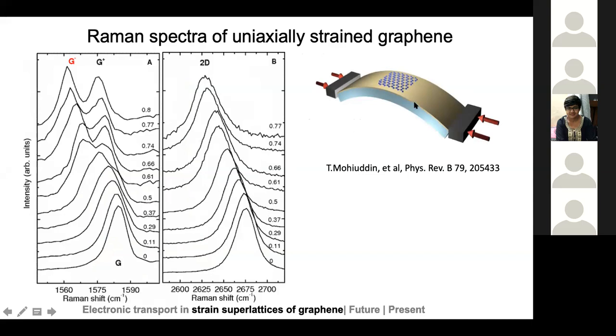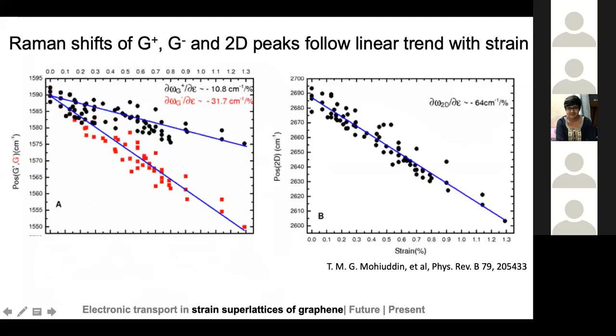In these experiments, different flexible substrates were used for bending graphene. And what was found was, in this graph, again, you have the intensity on the y-axis, the Raman shift on the x-axis. And what you'll find is as you increase the strain in the system, which corresponds to these different curves in the upward direction, the G peak slowly splits into two peaks, G plus and G minus. And the 2D peak, although it doesn't split into peaks, has a shift happening. And if you plot this shift in the two G plus, G minus peaks and the 2D peak, what you'll find is that all of them follow a linear trend.